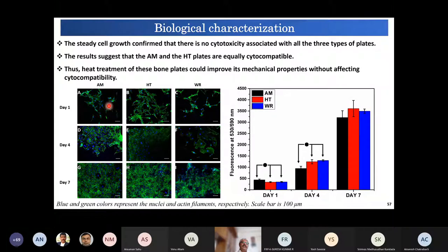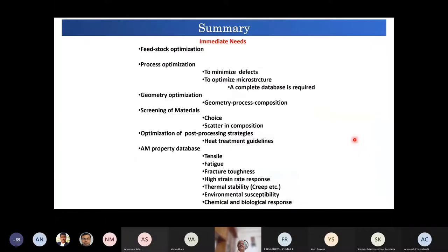And then we could see a cell growth rate. This was done in Professor Kaushik Chatterjee's lab. So cell growth rate on all these wrought materials and heat-treated materials, and heat-treated after additive manufacturing, and as additively manufactured material. We could see that the rate of cell growth was the best in additively manufactured material subjected to heat treatment. Even though there was slightly inferior performance of as-AM material, heat treatment has made it even superior to the wrought product. So this is what it is.